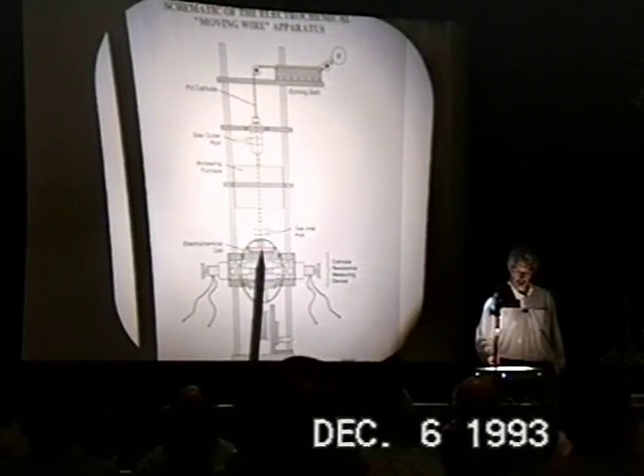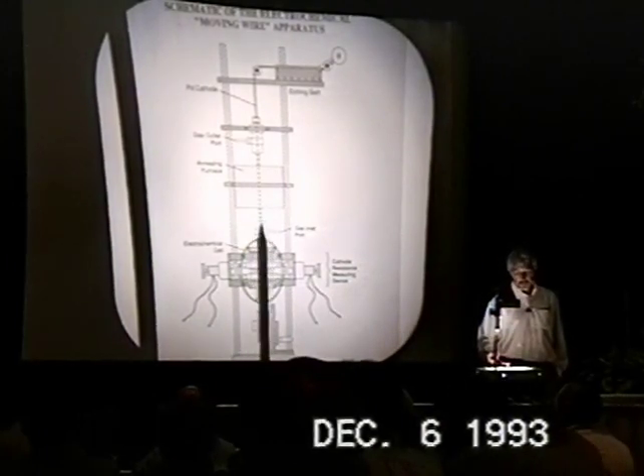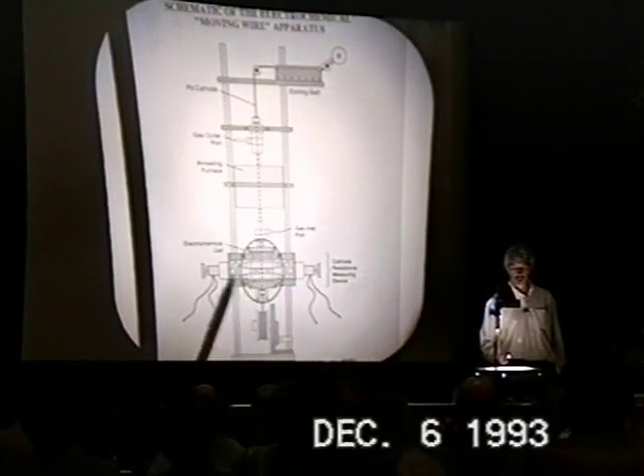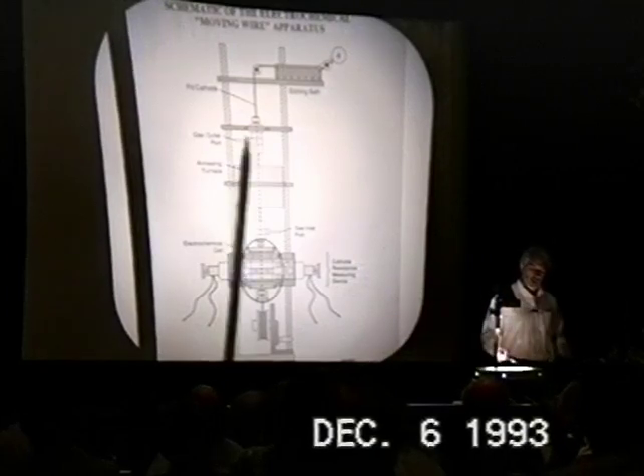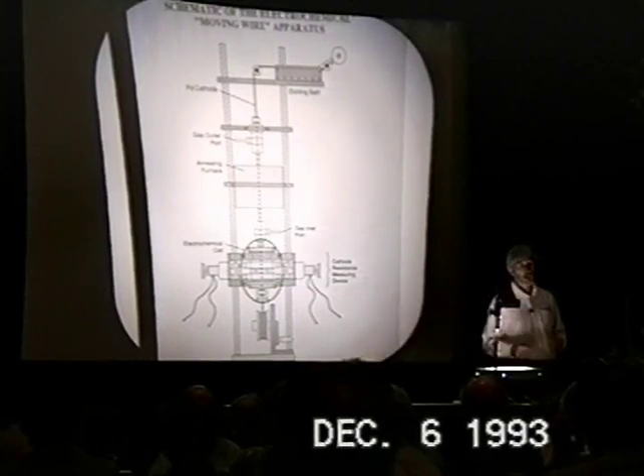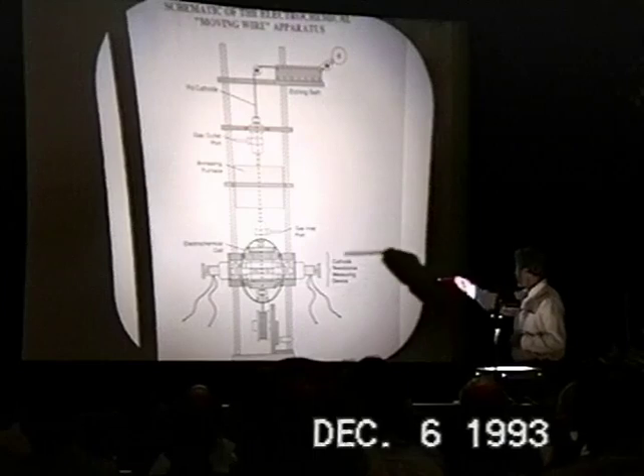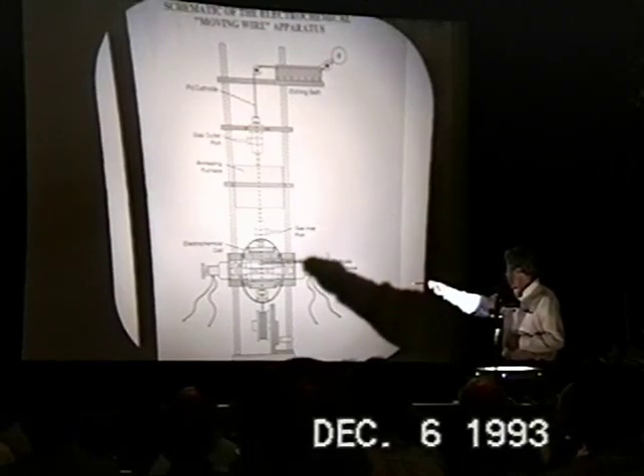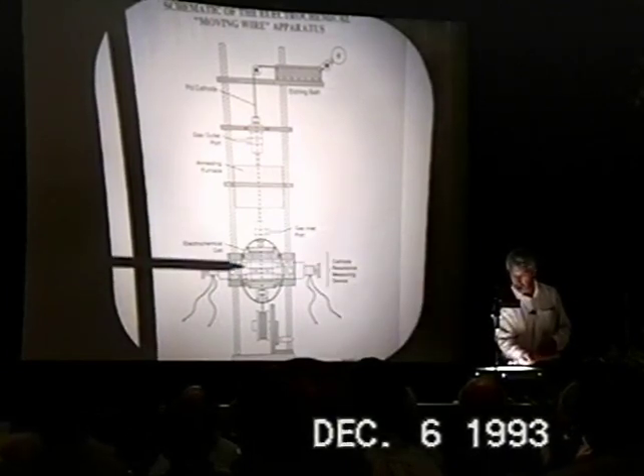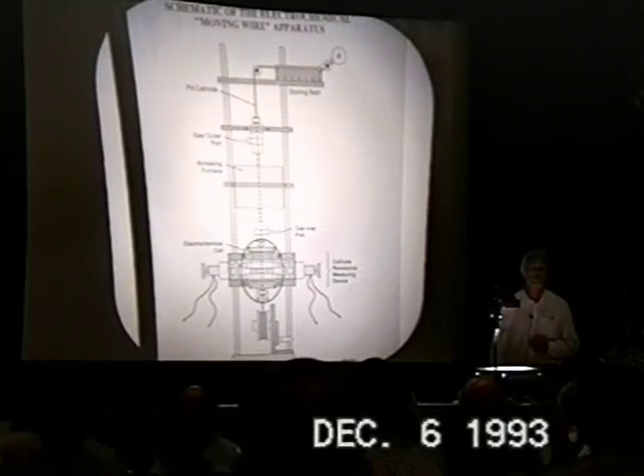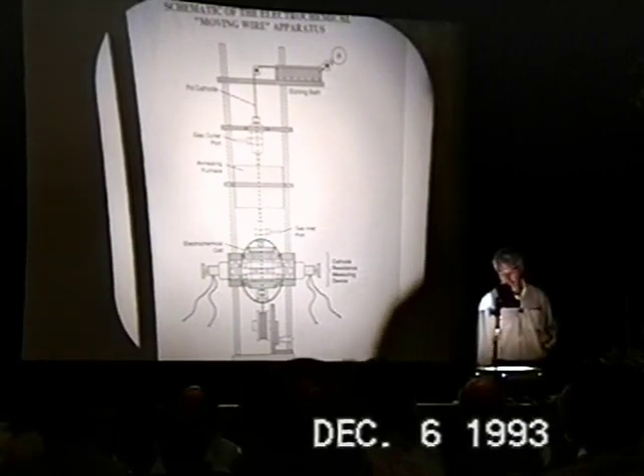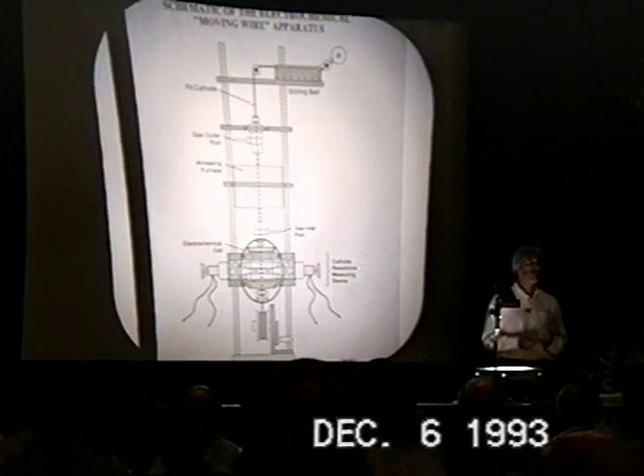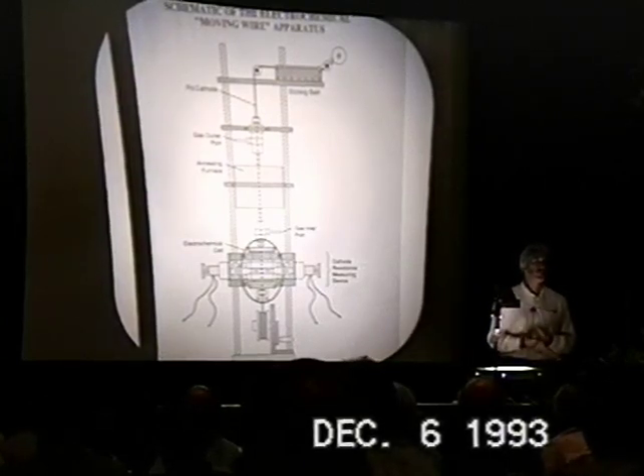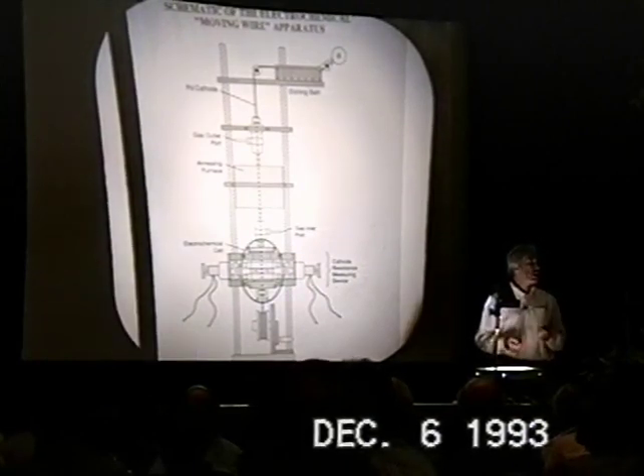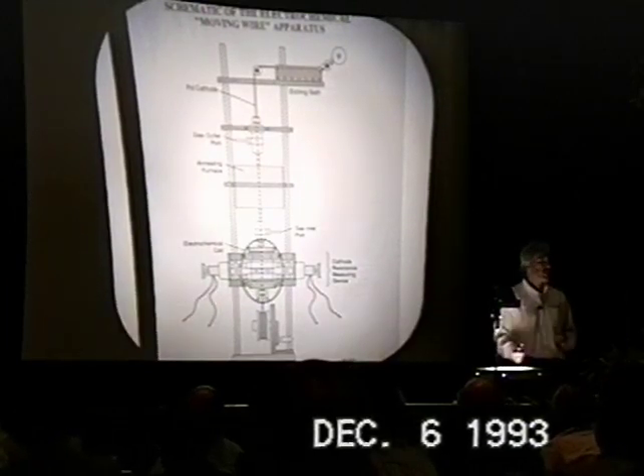Then the wire carries on through a region of preconditioning, where this section of prepared wire can be preconditioned in the way that we choose, and down into the electrochemical cell. So this wire has current contacts at the top and the bottom, and 4 solenoids drive contacts in and out. So this system drives contacts in to touch the wire and then back out again. So we can measure the resistance between this plane and this plane to determine the loading of that section of wire. We do a current time sequence on this cathode and measure the loading, voltage, time history of a particular section of wire, and either repeat it with the same wire or move in a differently prepared or identically prepared section of wire into this electrochemical zone for interrogation.